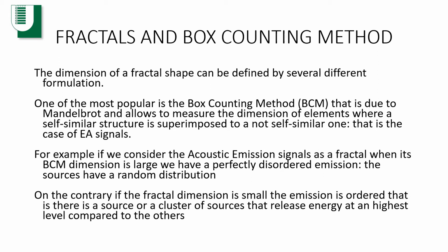On the contrary, if the fractal dimension is small, the emission is ordered, and this means that there is a source or a cluster of sources that release energy at the highest level compared to the others. From a mechanical point of view, this occurs when a material is under a damaging process. The method to measure the fractal dimension of a signal during time is the box counting method.